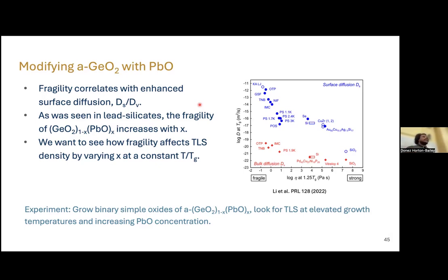Does that not help make the system more crystalline in the end, and you're still cooling it quickly after the deposition? I have seen that in particular in alumina, because I'm writing a paper right now on it. There's a maximum temperature above which we start to see crystallization in the sputtering. So with the data that I showed earlier, we were limited to 500 Celsius because at 550, we started to see signs of crystallization, and that's what we're trying to avoid altogether. For the E-beam films, crystallization wasn't the issue at high temperatures, but at high enough temperatures, you actually don't get any deposition. The atoms just bounce off the substrate and don't actually form a film.